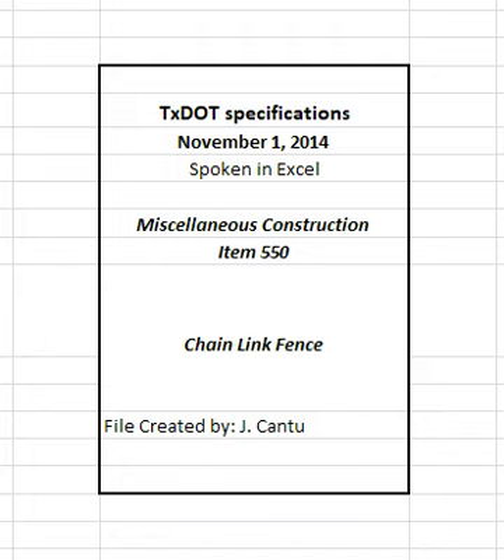2.15.2 Posts, braces, and gates. 2.15.2.1 Standard weight, Schedule 40, pipe. Hot dip galvanize inside and outside according to ASTM F1043, 1.8 ounce/square feet galvanized zinc weight.